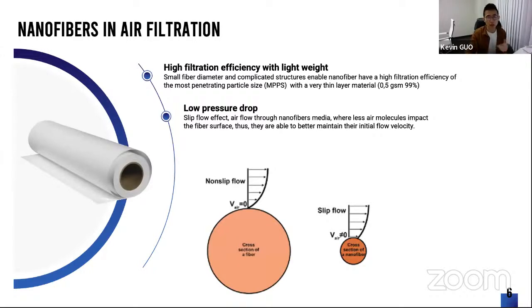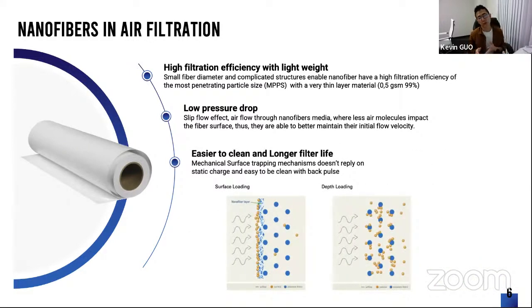If we look at this image, when air molecules travel through the nanofiber filter media, they have very little impact on the fiber surface. This allows the molecules to maintain their initial flow velocity, thus minimizing airflow resistance. In addition, nanofiber filter media also tend to have longer filter life and are easier to clean. The way nanofiber captures fine particles relies on a pure mechanical surface trapping mechanism. So the filtration performance doesn't deteriorate with time, unlike melt blown static charge filter media, so it can maintain this performance for a long period of time.